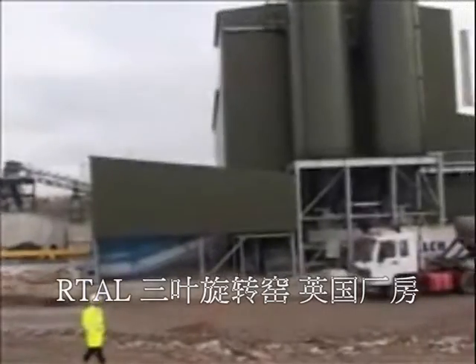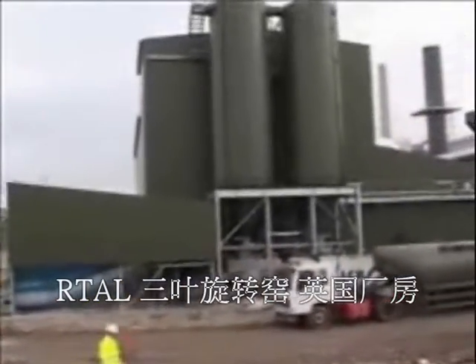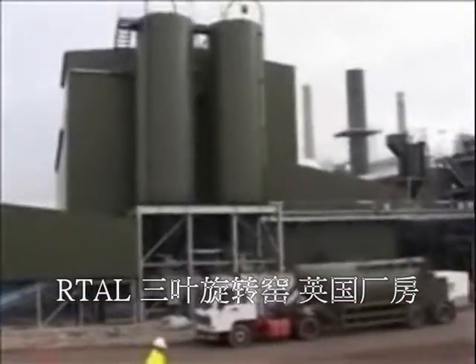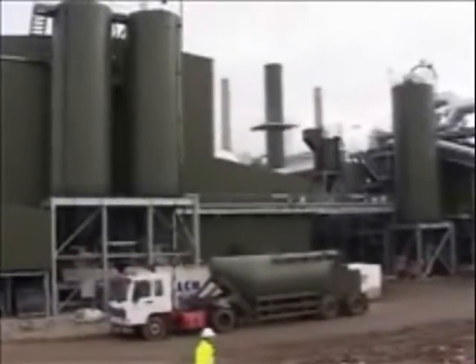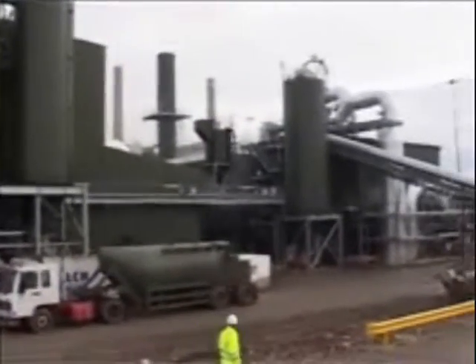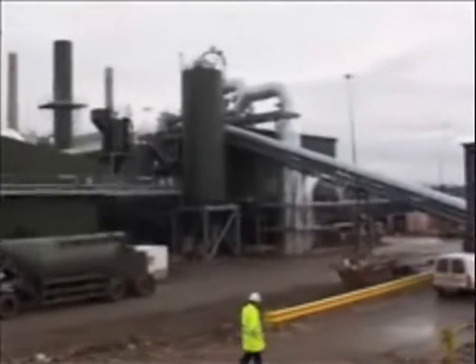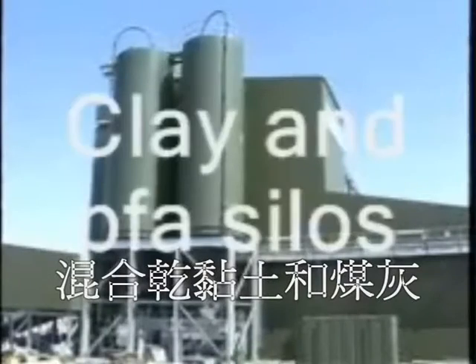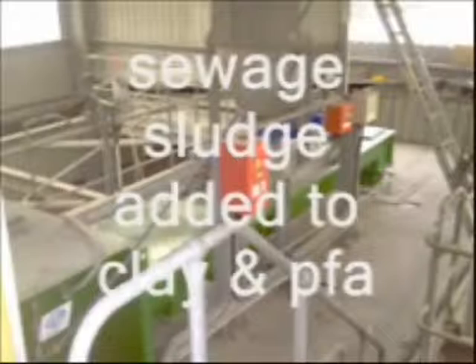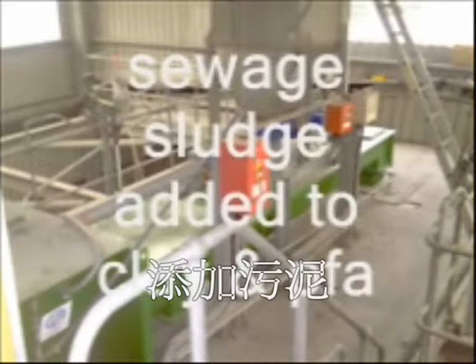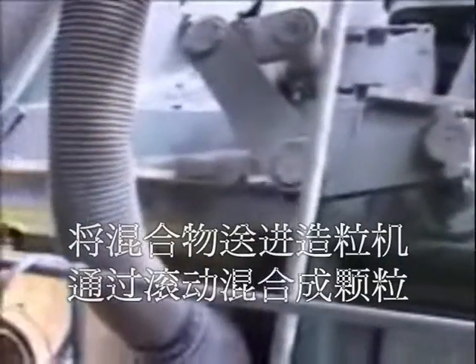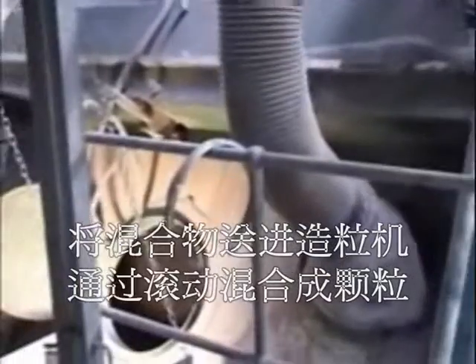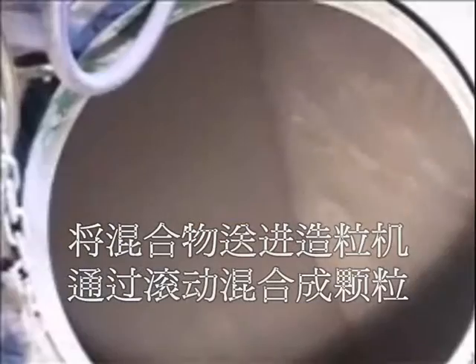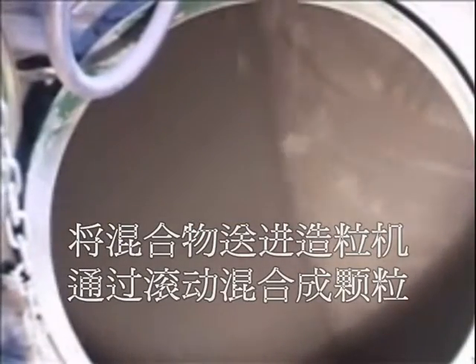The RTAL plant at Tilbury is split into two sections, the dry side where the aggregate is fired and the wet side for the dewatering of sludges. The process starts with ash from the coal-fired power station adjacent to the site in one silo and clay in the other. These two materials are mixed together and then sludge is added before being fed into a rotary pan pelletizer. The total mix at this point contains some 20% moisture.